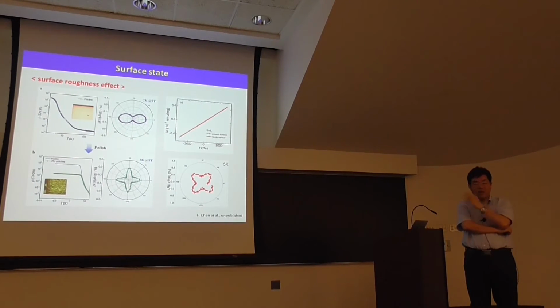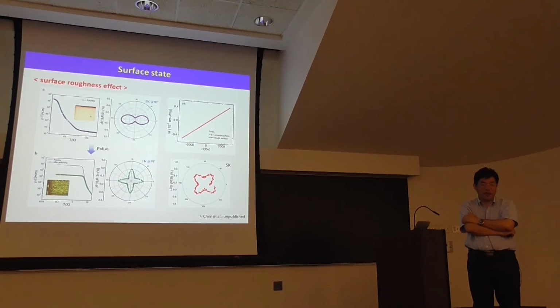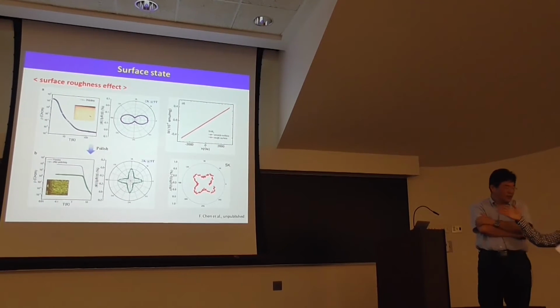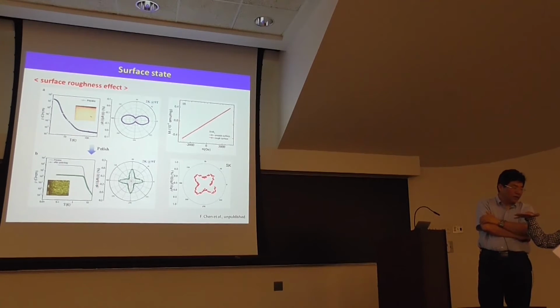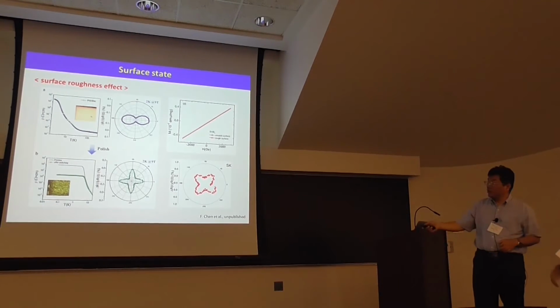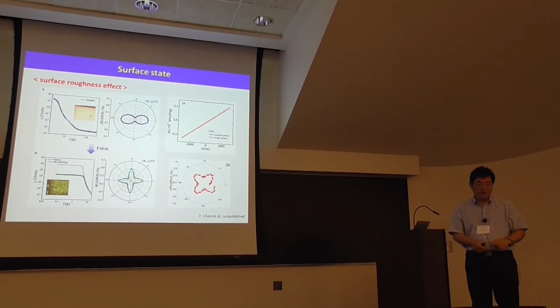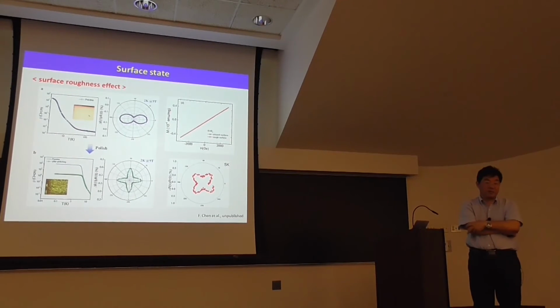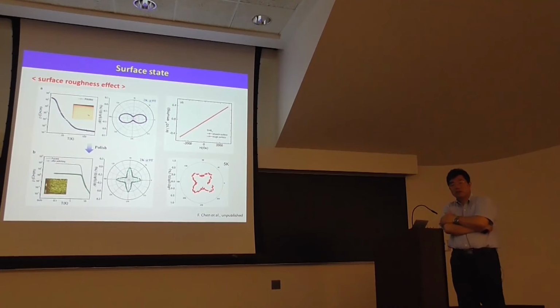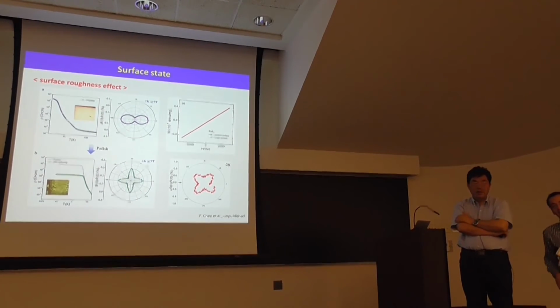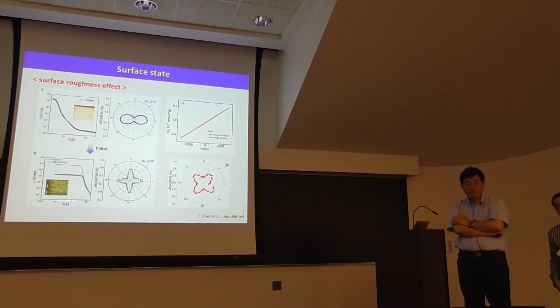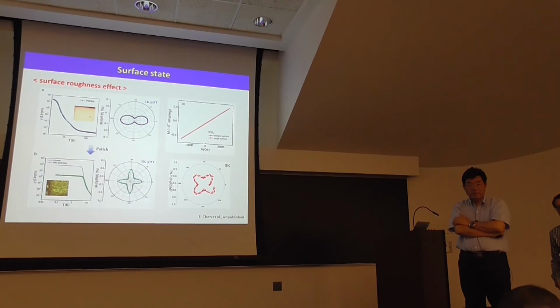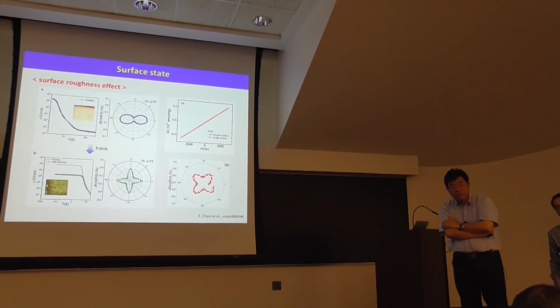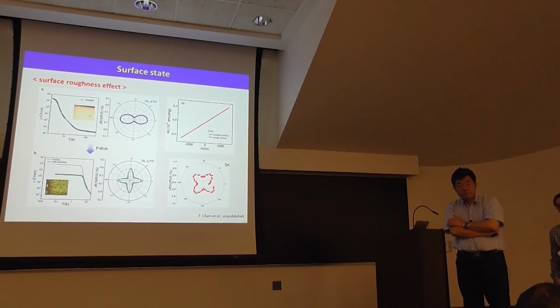But I think this is interesting. It's a huge change. Because presumably when you polish it, you're not changing the geometry of the crystal very much. Of course, we just polish it and measure it. It doesn't change any of that part of the behavior. I'll talk in a little bit about some work that we did that actually shows that when you polish it, you get some subsurface cracks in your material. And these cracks, insofar as they're defects, they're two-dimensional defects, they're new surfaces.